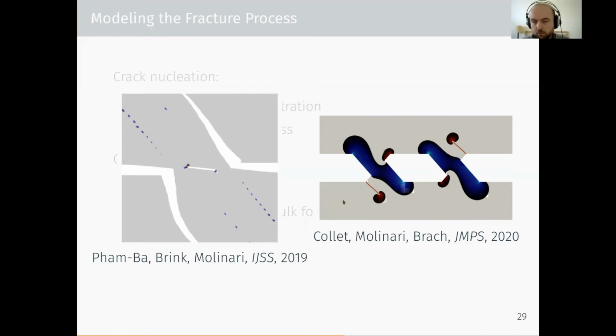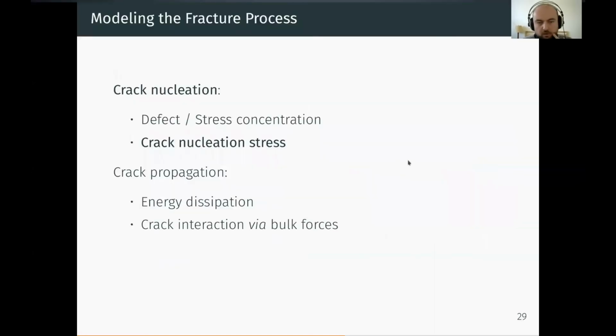You can also do it at the continuum scale. This is work actually by Stella and Jean-François, where they used gradient-based damage models. And you see the same thing here of a single crack that propagates due to the elastic interactions between the two asperity contacts. However, with the methods I've showed you earlier in this presentation, I can only do elastoplastic contact. I cannot do crack propagation yet. That's something I'm interested in, but cannot do currently.